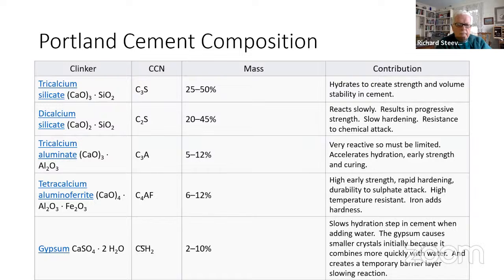So the cement, for example, that's used in a nuclear reactor shell would be different than the cement that you would use to pour a sidewalk. The requirements, and probably the testing as well, of the two are quite different. And yet again, different is something that you would line a chimney with. For example, to line a chimney, you put a lot of alumina in there. You end up with a Portland cement that is very resistant to temperature, but it's prone to sulfur attack, for example. So there are these trade-offs in cement.